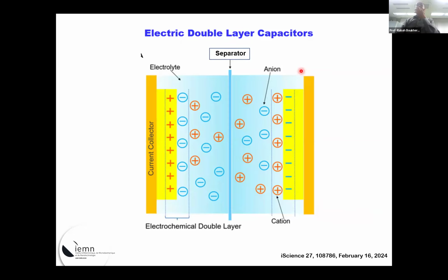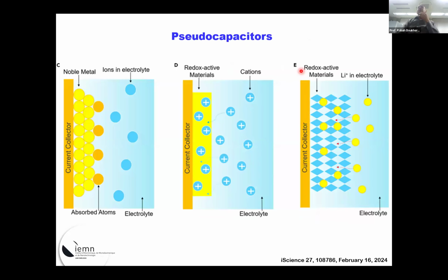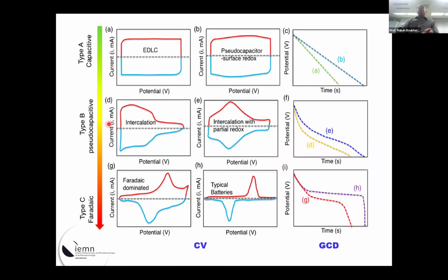I'm not going to go into too much detail, but this is just a normal electrical double layer capacitor, where you store the energy in the form of charges. The same applies to what you call redox active materials or pseudocapacitors, where you have either intercalation, but also Faradaic materials where you have electrochemical reactions. The typical one in metal oxides is ruthenium oxide, which also works very nicely as an EDLC type material. That's the typical thing when you start in the field: a pure EDLC will have this really nice form.